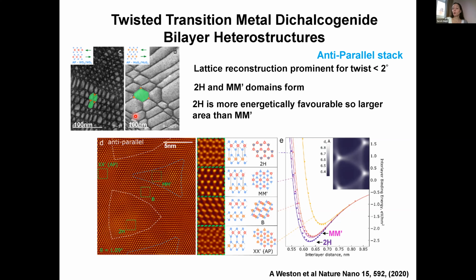Now, I mentioned that we're doing this in a scanning transmission electron microscope. I should have said that this allows us to only slightly change the settings and also get atomic resolution scanning transmission electron microscope images. And this really is a nice way to highlight the different stacking domains. We can zoom in on the different stacked regions, and of course, matching to simulations, really understand what's going on at an atomic level, even when we've got defects.